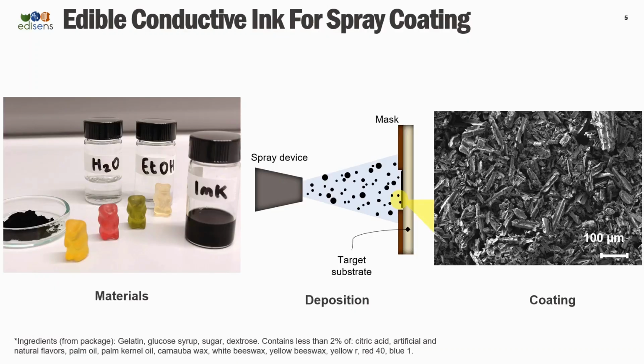So today I'm going to focus on activated carbon, and a blend of activated carbon and gelatin. And just to be provocative, we used Haribo's gummy bear to show that you can actually use normal gelatin. And the conductive ink is only made of gelatin, ethanol, water, and activated carbon. And it's spray-coated onto any substrate using, for example, a mask so that you can pattern it. And on the right, you can see an example of how the coating looks like. So that's the morphology. You can basically see that there is an agglomeration of activated carbon held together by gelatin.